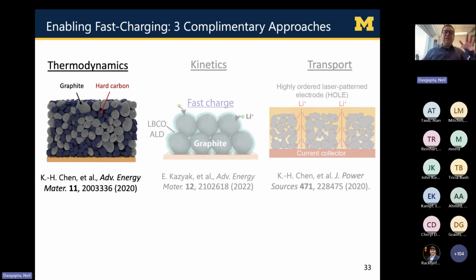So that's one approach. The second approach we took was more putting our thermodynamics lens on. So here we said from a material science standpoint, graphite has some limitations. Are there other materials we could start to blend into the graphite electrode to improve its fast charge capability? Here we look back at an old material that was studied back in the 1980s quite heavily, hard carbon, right? This is actually a byproduct of the petrochemical refining industry, right? It's a pretty low cost carbonaceous material.